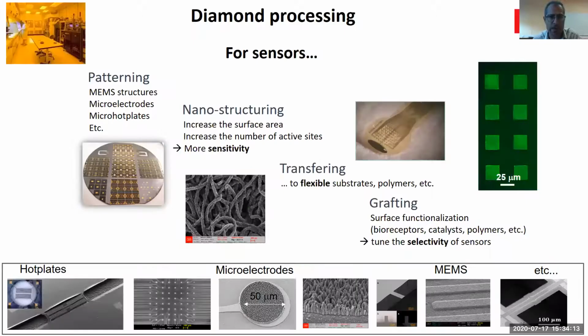So what can we do with these diamonds? We can do some microstructuration. This is mostly done in the clean room. This is, for instance, a 4 inch silicon wafer that is covered with diamonds. You can see a lot of structures here. The dark areas on the wafer are diamonds. Then we have gold contacts to get some electrical contacts. And we can make in this way a lot of different sensing technologies, microelectrodes, resonant devices, micro hot plates, and so on for sensing applications.